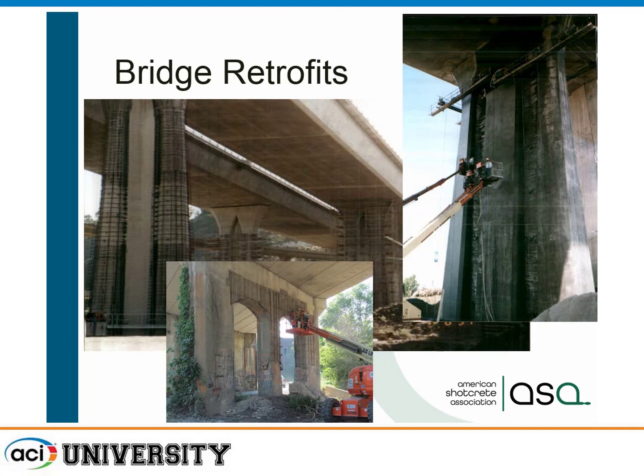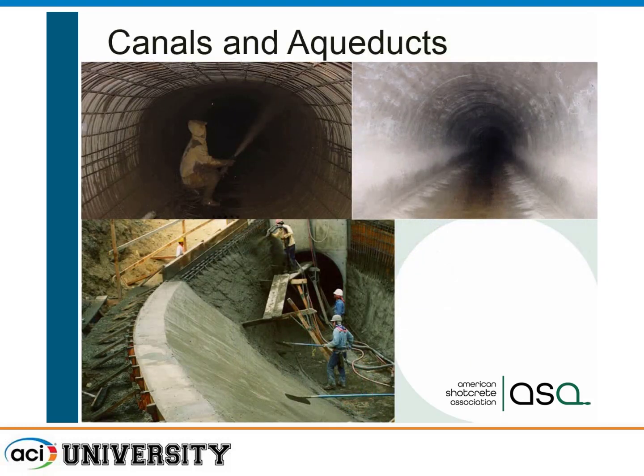Here you can see large bridge retrofits where we're coming in. It's been used extensively for seismic retrofits. I know the WRAP document is about repair, but it could also be for seismic strengthening. Getting back once again to sound substrate and then putting your reinforcing up in this case and then shotcreting in place. Another big application we see is in culverts, sewers, water lines that have been corroded, coming in, actually getting back once again to sound substrate and adding shotcrete concrete in place.